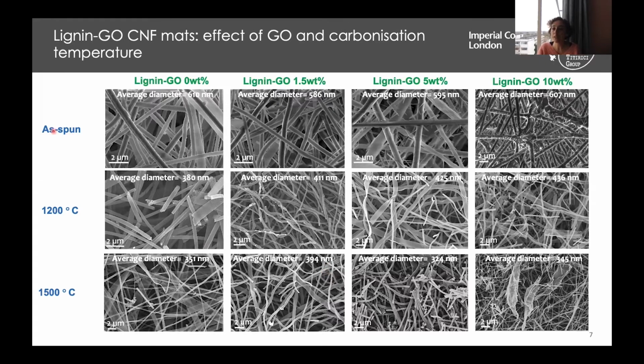So when we observe the as-spun fibers, we can see that by increasing the weight percent of graphene oxide, we see the appearance of these elongated features. And we believe that that is happening because the graphene oxide, due to the high ionic strength of the solution, due to the concentration of sodium hydroxide, is coagulating and partly being reduced in the solution. These features are completely disappearing when we carbonize the samples at 1200 degrees and 1500 degrees.